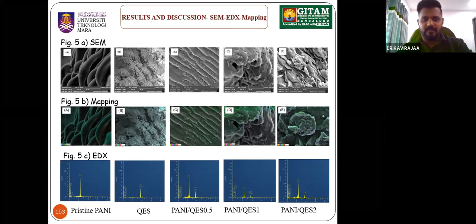And also the mapping, if we can zoom in, you can see a lot of dots for the calcium, which indicates that the mapping and also the EDX further prove the integration of the polyaniline and the cockle eggshells. Basically, from cockle eggshells, we are focusing on the calcium carbonate. So they have complemented each other.